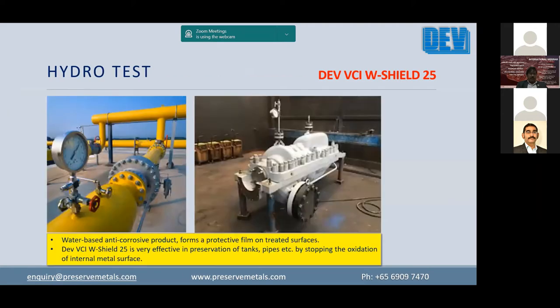And this is a sample of the testing arrangements that was done using the WS25 additive. Even after draining, it provides both immersed surface protection and aerated surface protection by forming a monomolecular layer of protection. Compared to traditional methods, which have a limited period of preservation, you don't have to do continuous monitoring as in the case of nitrogen purging. Instead, you complete the test, seal the ends, and leave it there until it is put to use.